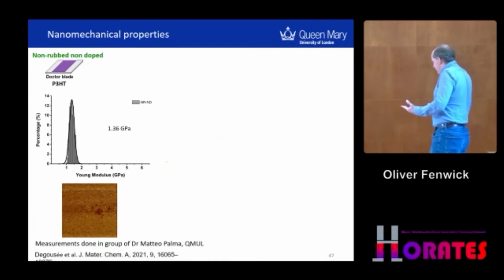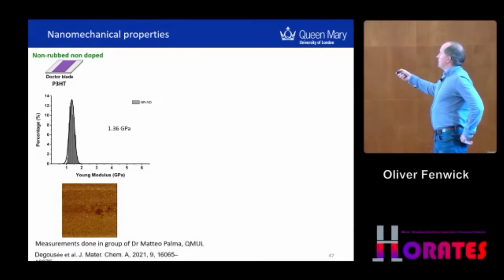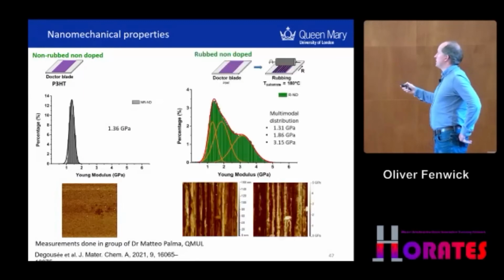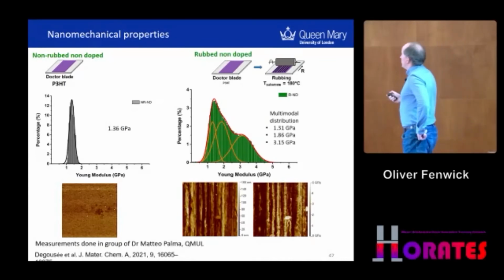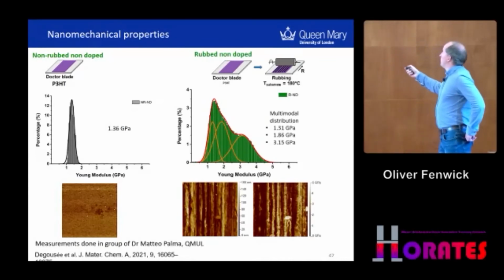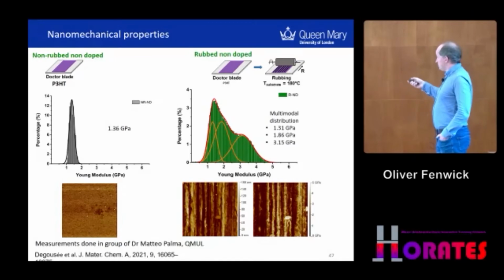What else changes? When we think about what else would depend on the alignment to change, we decided to look at the stiffness of these films. This was done by nanomechanical analysis, using an AFM tip. We found that the Young's modulus of an unrubbed film was around 1.36 gigapascals. Rub the film, and it becomes a little bit more complex. You still see something around 1.3 gigapascals, but also components at much higher stiffnesses.